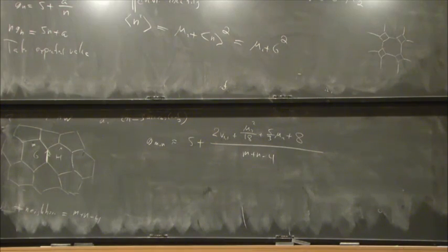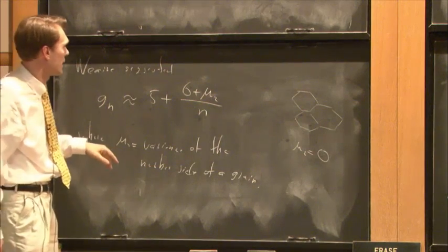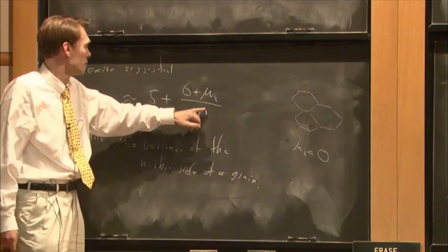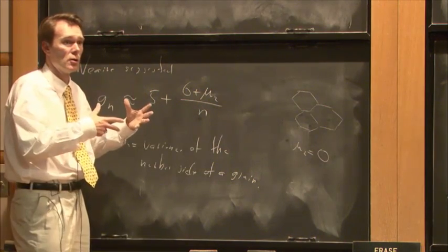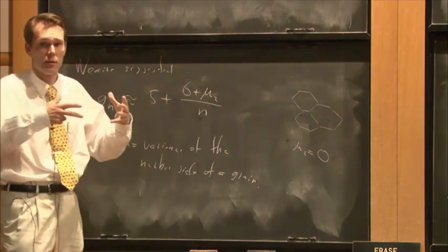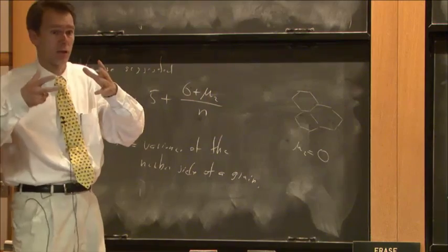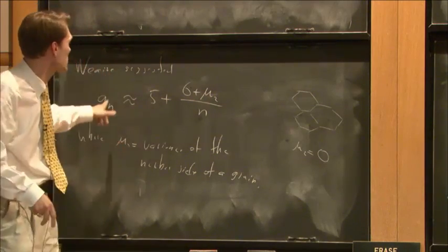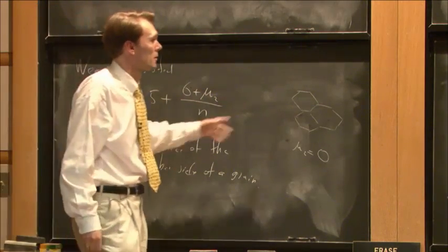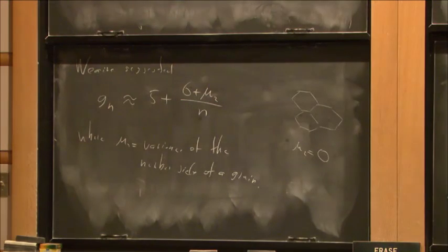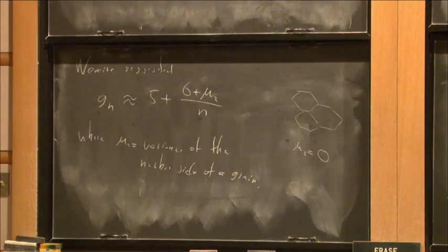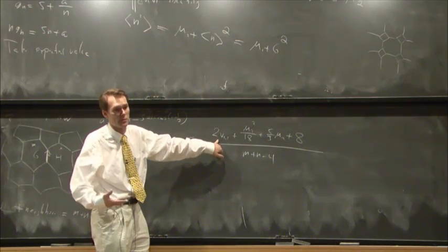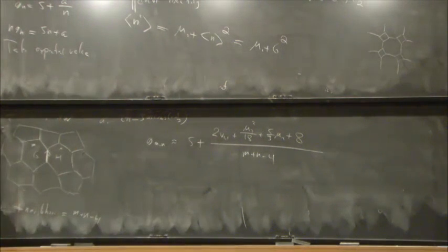So it actually does say something: that a large grain would have neighbors that are small, and a small grain will have neighbors that are large. Agree? There's an inverse correlation here, and in order to press this law further, I would have to use the covariance here, which somehow is a beautiful thing, that Weaire's law doesn't have the covariance in it.